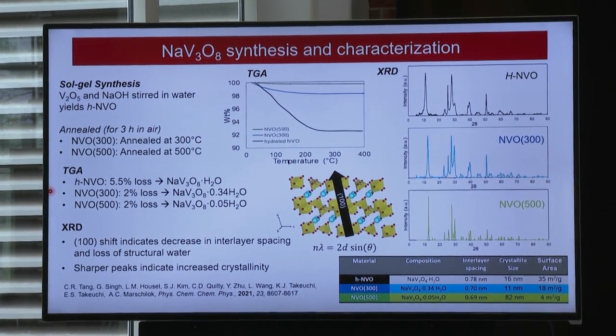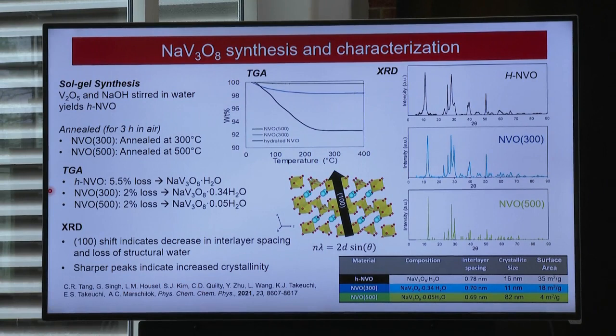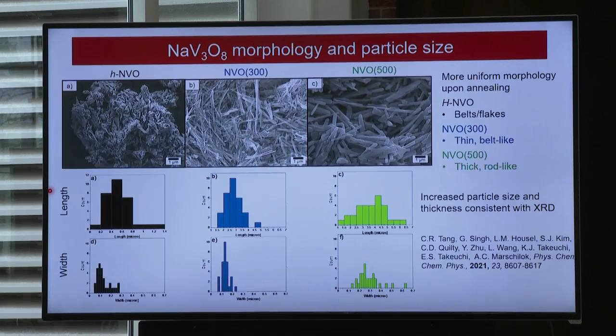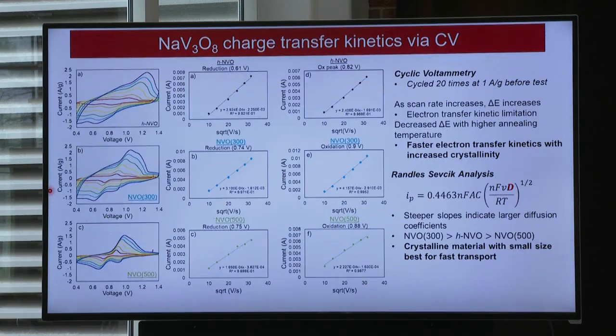So with the as-prepared material, H just means hydrated, there's a lot of water present in these layers. If you heat it to 300, there's a few percent. If we heat it to 500, the material is close to anhydrous, not quite, but close to anhydrous. So we have three different material systems that we explored. It also affects the morphology. After heating, the material turns into nanorods, and at a higher temperature, the nanorods become thicker, bigger.